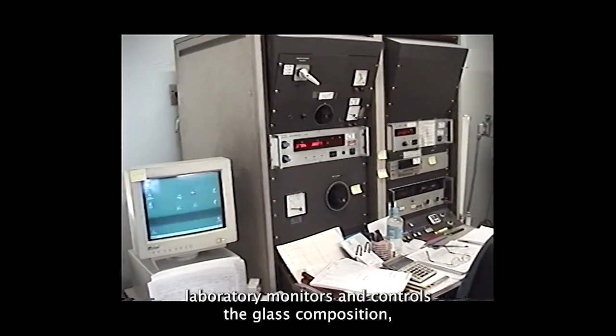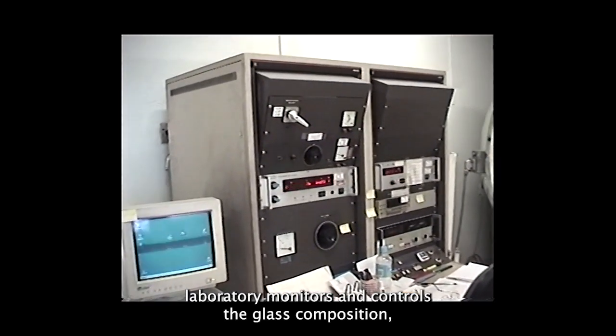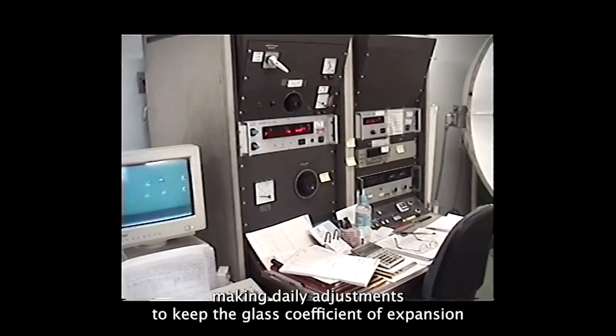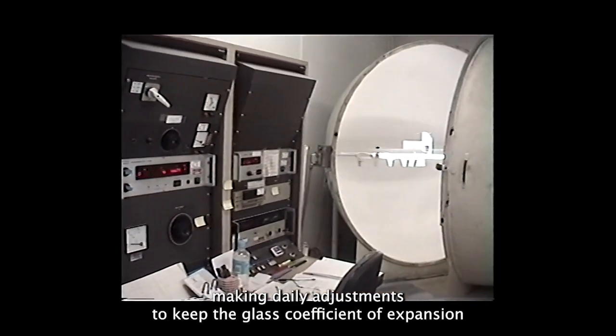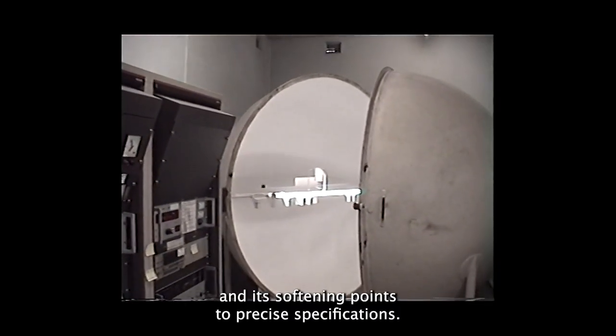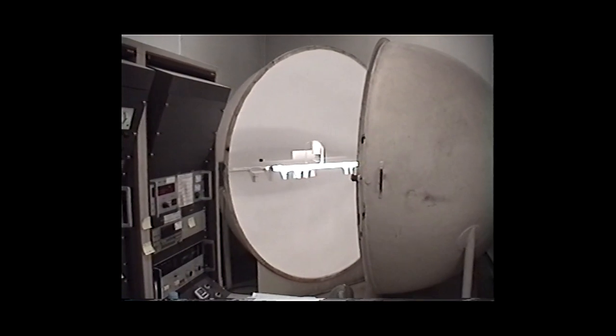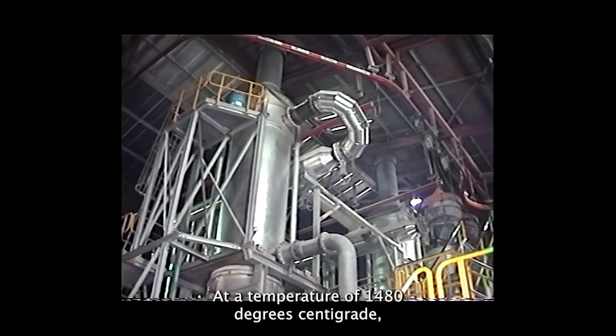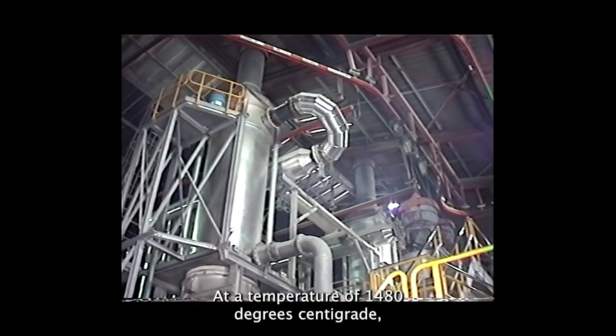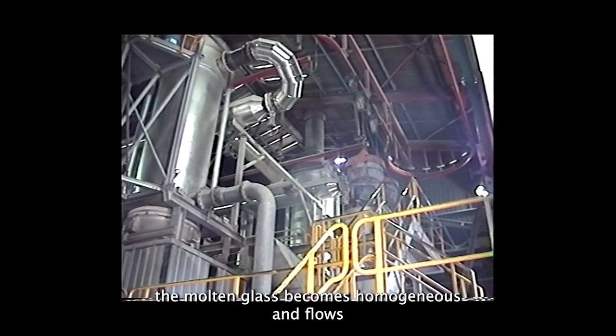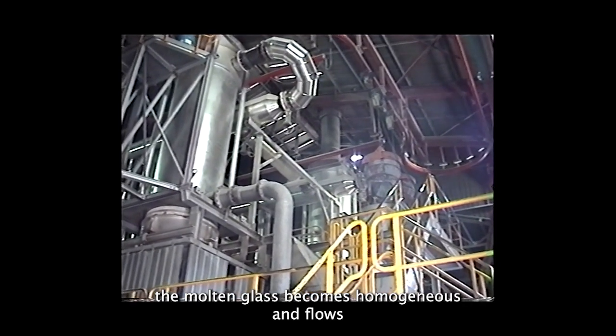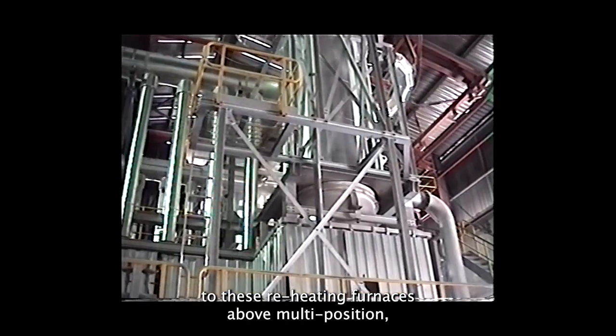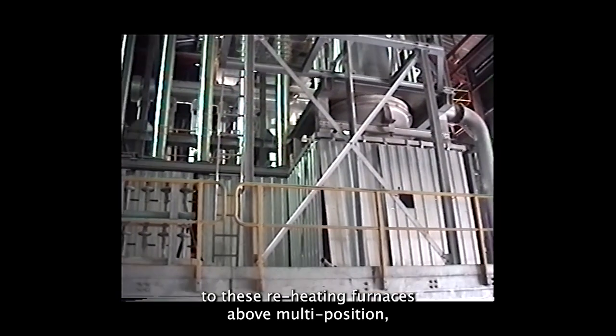An on-site laboratory monitors and controls the glass composition, making daily adjustments to keep the glass coefficient of expansion and its softening points to precise specifications. At a temperature of 1480 degrees centigrade, the molten glass becomes homogeneous and flows to these reheating furnaces above multi-position pneumatically operated bulb blowing carousels mounted with 16 perpendicular blowing heads.